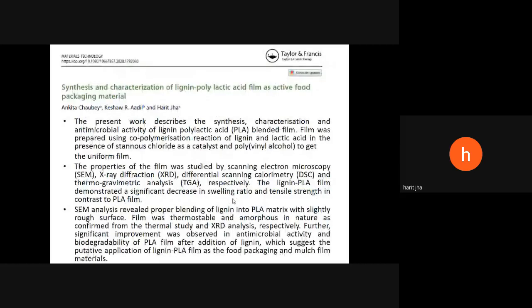This is another work which we have recently done. It is on synthesis and characterization of lignin polylactic acid film as active food packaging material. In this work, we describe the synthesis, characterization, and antimicrobial activity of lignin polylactic acid blended film. The film was prepared using co-polymerization reaction of lignin and lactic acid in the presence of stannous chloride as catalyst and polyvinyl alcohol to get a uniform film. The properties of the film were studied by SEM, XRD, DSC, TGA. The lignin PLA film demonstrated a significant decrease in swelling ratio and tensile strength in contrast to PLA film.